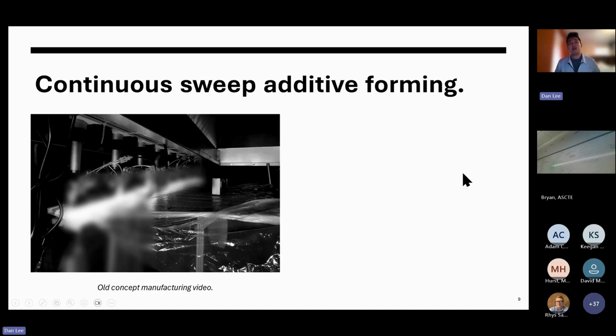So here's a video of our very first, I would say, large-ish piece. It was about 4 feet wide by 6 feet long, with a laminate thickness of about 1/2 inch. If we look here, this laminate started at 1/2 inch thick. Here it's flat, and then we use this to demonstrate. As we're pulling, we're going to change it from a flat to an arc. Obviously this is already cured, so it stays flat on the right end, and then it's arced coming out of the machine. And you can see it over here.